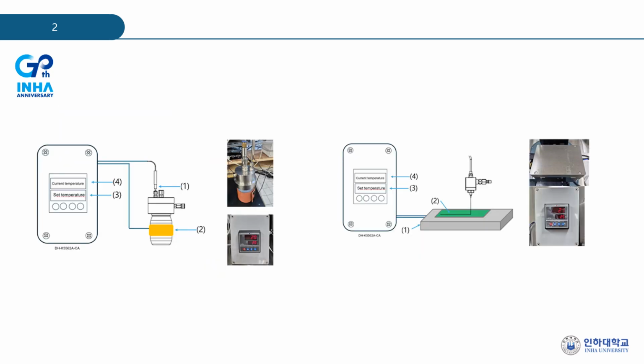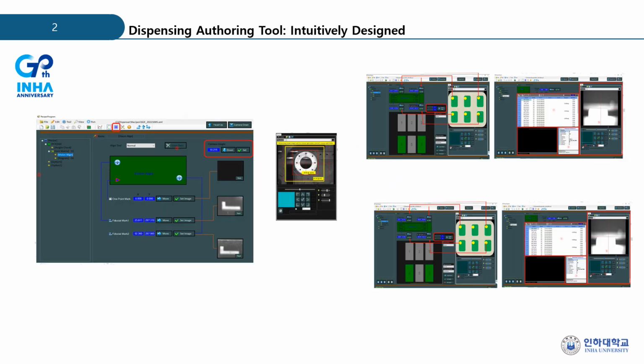Additionally, we have developed a system that allows temperature control of the atomizer with ink and the substrate to be printed up to 300 degrees, enabling simultaneous sintering. We also developed a G-code-based system so that it can be used in the same way as existing competitors. In addition, we used the dispensing authoring tools of the semiconductor dispenser so that it can be used intuitively and can be used in the semiconductor manufacturing environment as before without additional training.